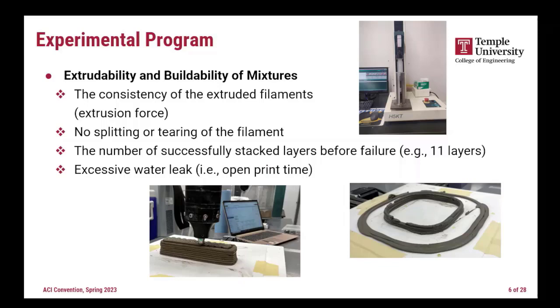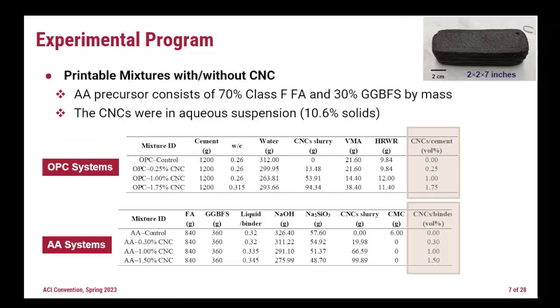The splitting and tearing, obviously you are familiar with this, right? This is not an acceptable system. And regarding the buildability, we looked at how many layers we can stack. Since we were interested to print a 2-inch by 2-inch geometry, we printed around 11 layers. And if we didn't see extensive deformation, then that was acceptable for us. And also in some systems, we saw excessive water leak from the nozzle due to the separation of the material. So that wasn't a printable system either.